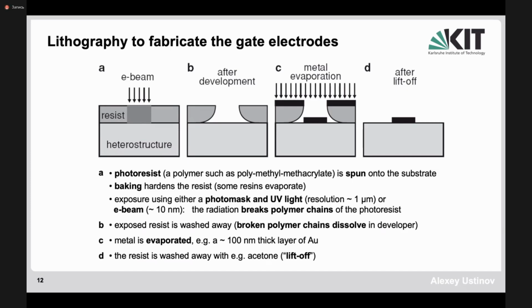But just to give you an introduction, the technique is shown here. Basically, you use the electron beam, which is focused on a thin layer of polymer called resist, which is deposited on the heterostructure. So you put some liquid with this polymer, then you dry this in the oven, and then you put this in the electron microscope or e-beam lithography unit with an electron beam, and then you draw a line with the electron beam.